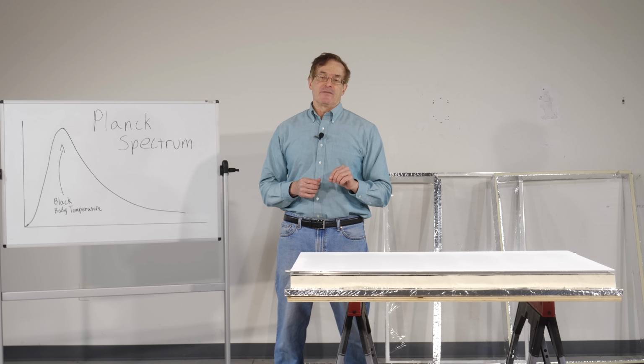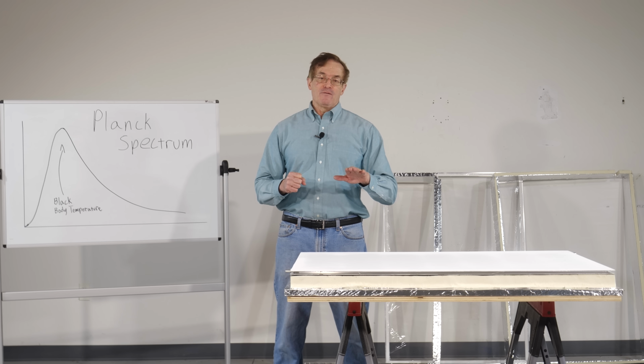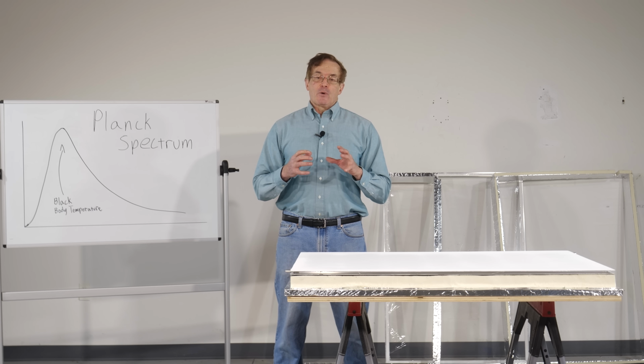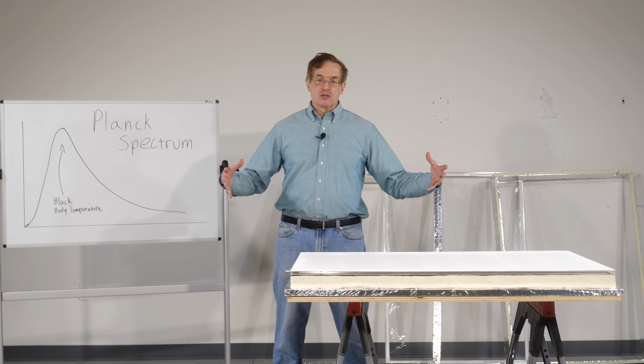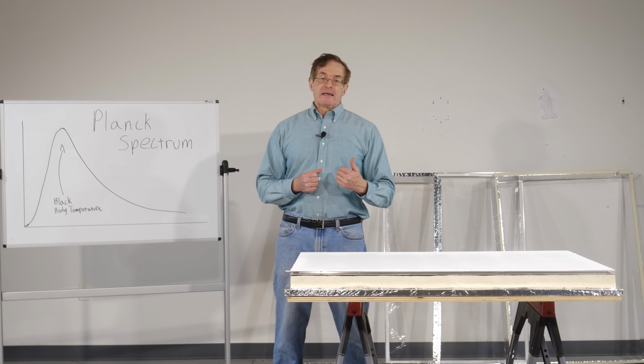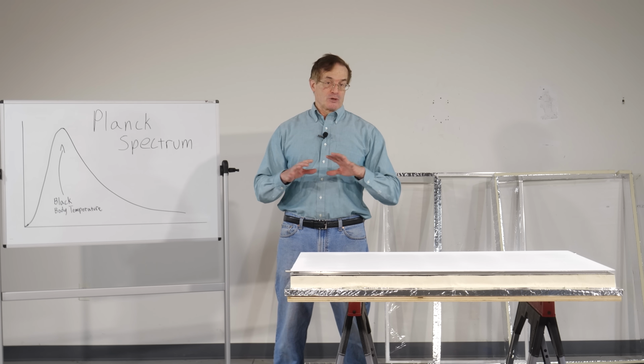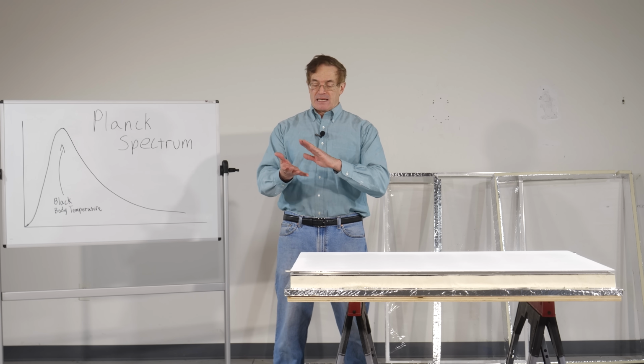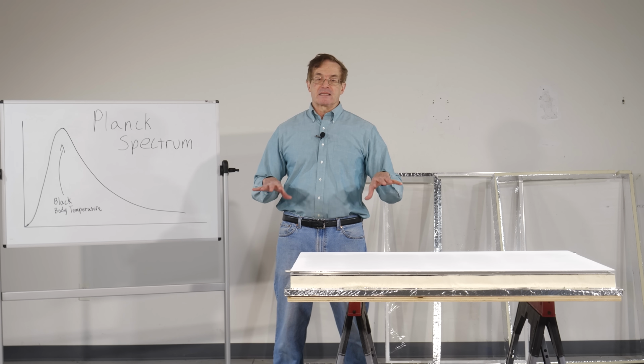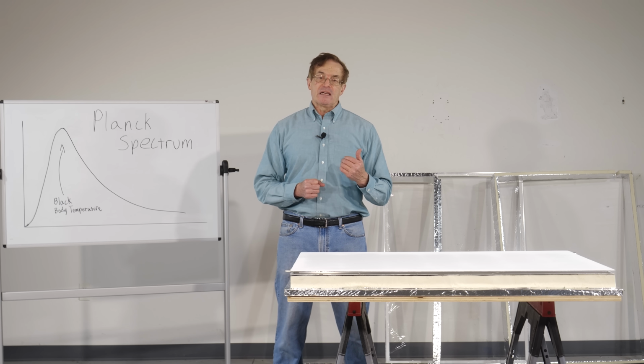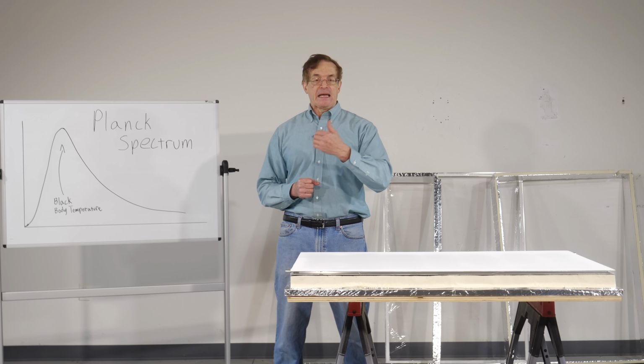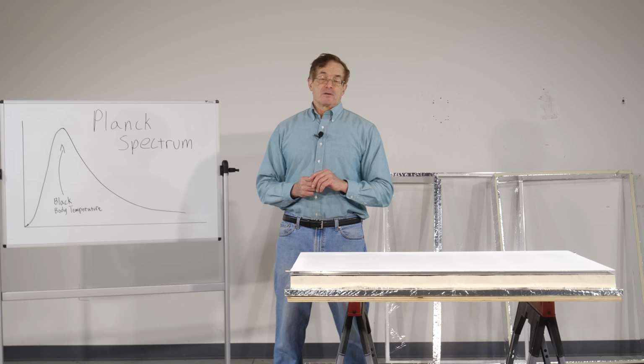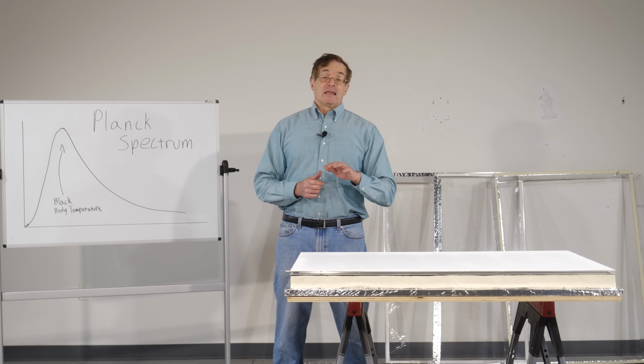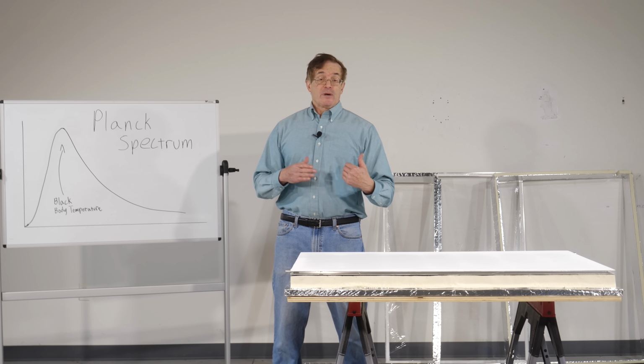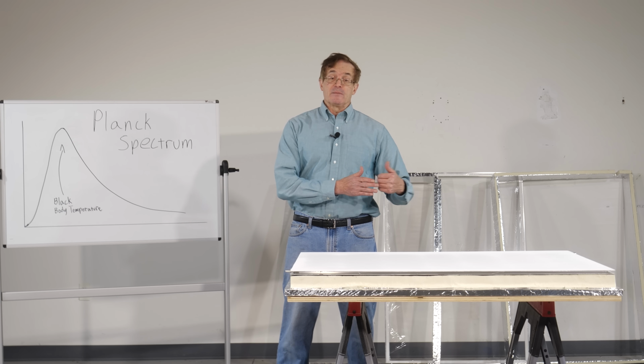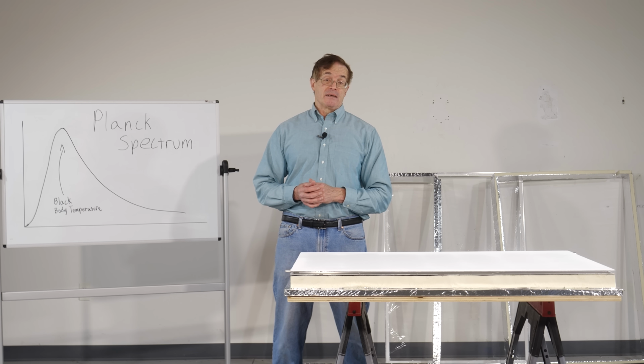It's called emissivity, and you can think of this as sort of the inverse of reflectivity. It represents the percentage that any real surface, any real object, will radiate compared to a perfect black body emitter, which doesn't exist. Typical objects like skin, cloth, commercial paints, concrete, wood, plastics, all have emissivities that run around 75 to 85%. Certain materials that are very reflective in the infrared, like polished metals, like aluminum, have very high reflectivity and as a result, lousy emissivity. A polished aluminum is around 6%.